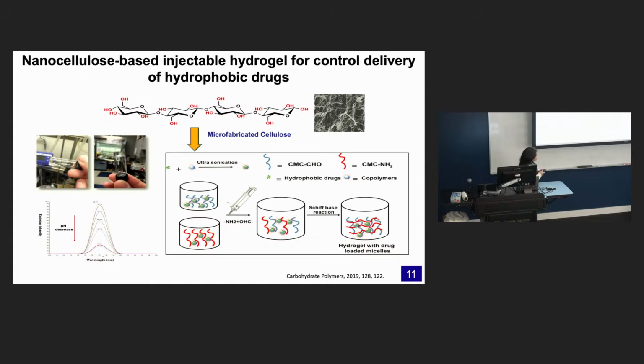This research mainly starts with nanocellulose as a starting material, and using a Schiff-base reaction, we can form the injectable gel. I think it takes a few seconds, less than 10 seconds. We can adjust this by adjusting the grafting. Oh, sorry, I think this doesn't work anymore. That's fine. Based on this, by tuning these end groups, we can make the gel really injectable, and it can form the gel in 10 seconds.